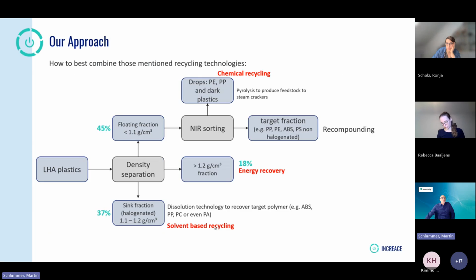So in the end, just to give you an indication, these different technologies do not always have to compete with each other, they can even work hand in hand. This has been exemplified in our INCREACE project for large household appliance plastics. Here we made use of the sink fractions, where we used solvent-based recycling to recover ABS, PC, but also polyamides and polypropylene highly filled with glass fibers.